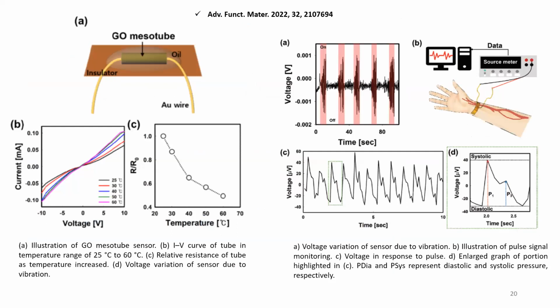As a proof of concept, we used this single mesotube as a sensor. How we prepared the device was quite simple. We took an insulator, took a single mesotube in a wet state, put it on a polyimide tape, and dropped oil on it to prevent shrinkage and drying. Two sides of the mesotube were attached to gold wire fixed with a silver paste. It was attached to a Keithley device to get the IV curve. As you can see at the left bottom picture, figure C, the resistance decreased by increasing the temperature.